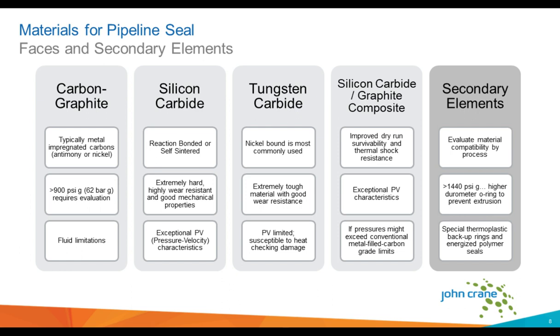Tungsten carbide overcomes that. It's very resistant to mechanical and thermal shock. It's a very dense material, cemented carbide, typically using a nickel binder agent in addition to the natural tungsten. The disadvantage of using tungsten carbide is that while it's very mechanically tough and resistant to thermal and mechanical shock, it's very susceptible to heat checking, which is a little bit of localized cracking of the subsurface of that material due to expansion and contraction from rapid heating and cooling. So heat checking damage is irreversible and typically results in much higher leakage once it does occur.